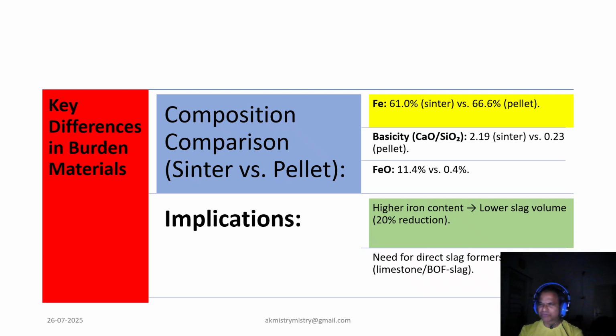Now the basicity dropped from 2.19 to 0.23, as shown in the slide, necessitating the use of direct slag formers like limestone and BOF-slag. So this also gives us a learning that when we concentrate on a burden matrix of higher pellet percent, basicity becomes a challenge. And we have to add some basic components like LD slag or limestone to tune our slag basicity.